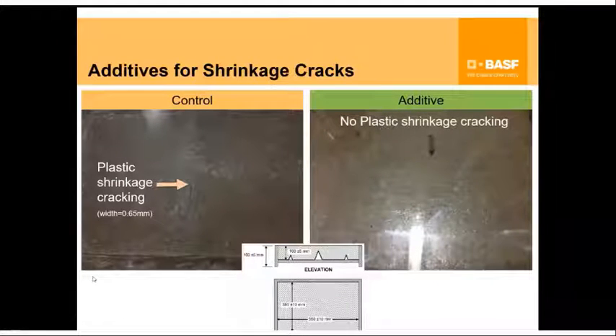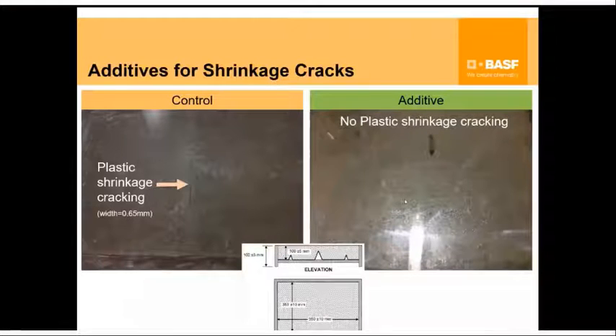This is a classical ASTM C1579 test, which you can use to measure plastic shrinkage cracking or look at the propensity of plastic shrinkage cracking. This is a very exaggerated test that includes temperature control, humidity control, as well as a wind speed that is artificially built in to exaggerate this effect. But again, there are additives that can help prevent this plastic shrinkage cracking. You would see these kinds of cracks mainly in elements that have a high surface area, like a slab, for example, or a floor. Hence, you will hear more from Piyush on this.